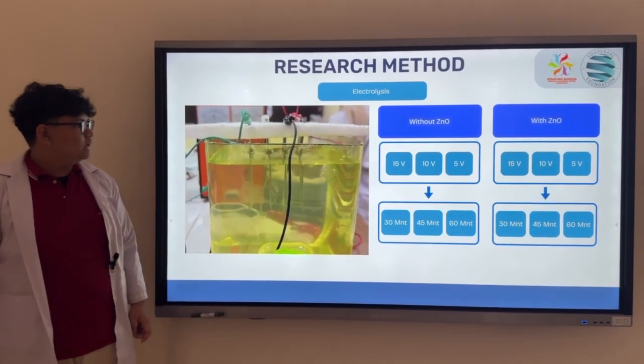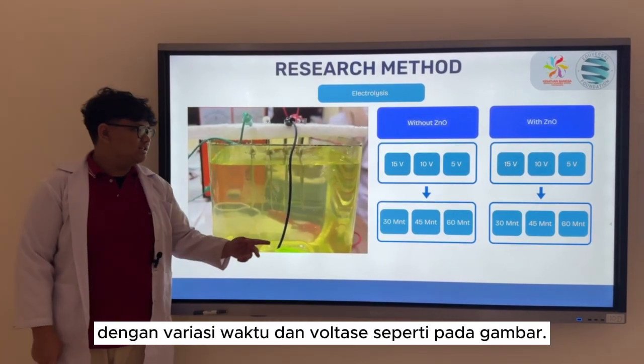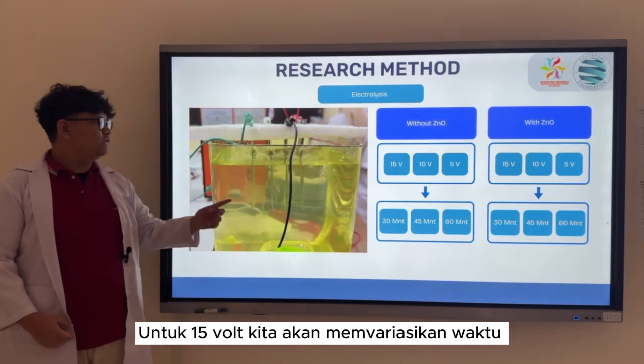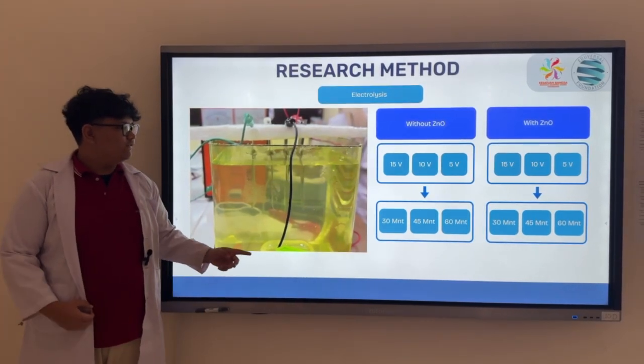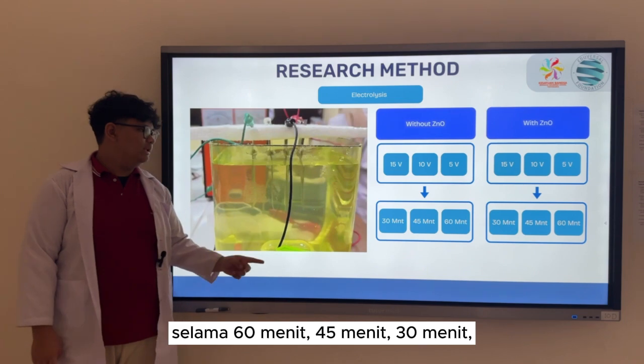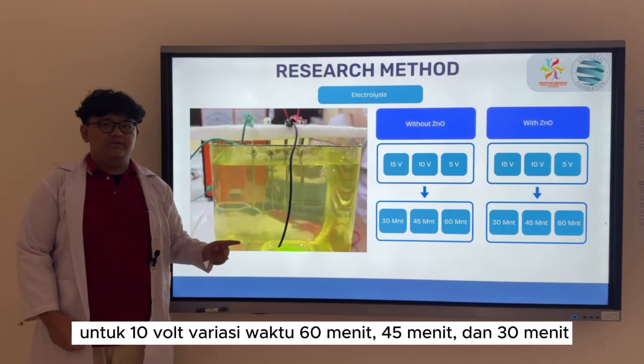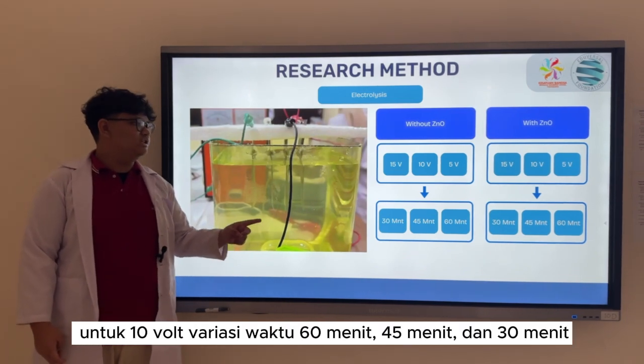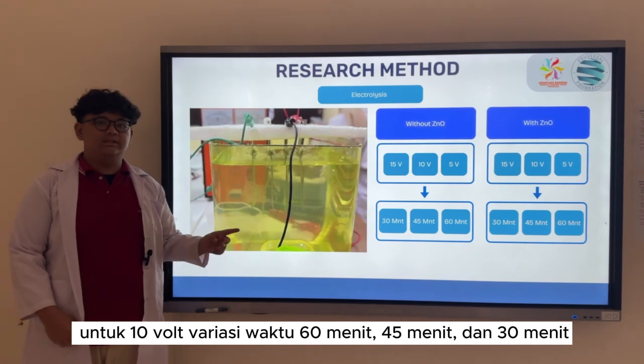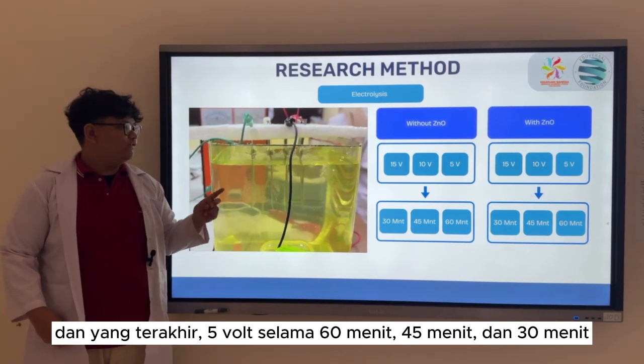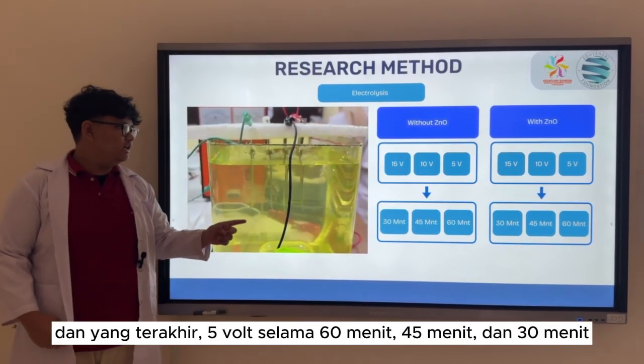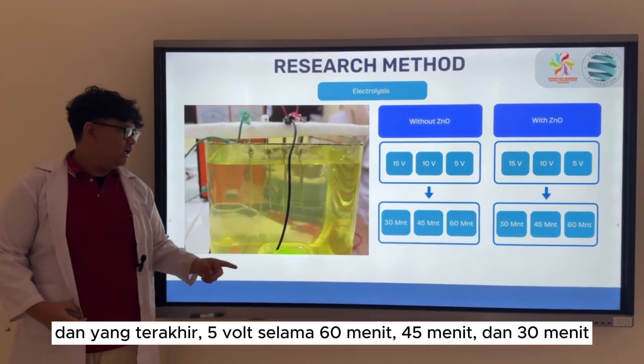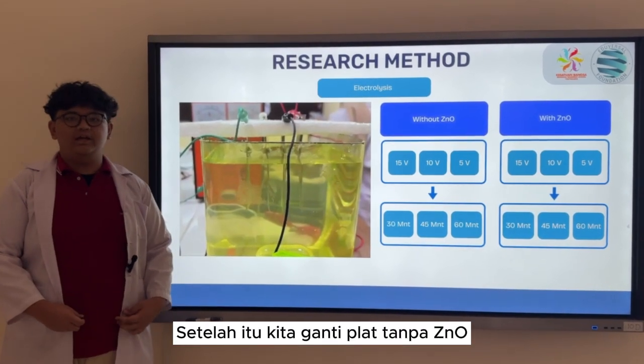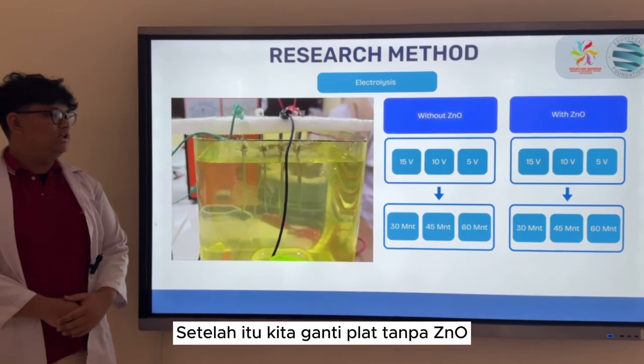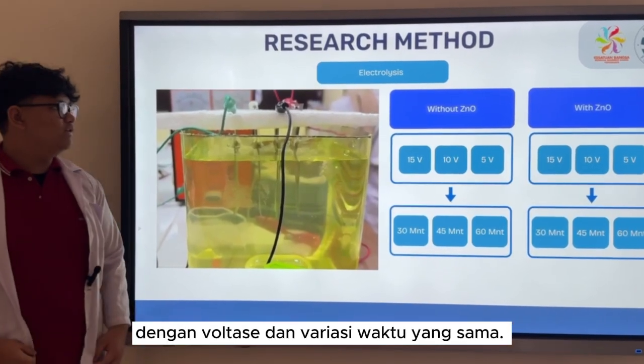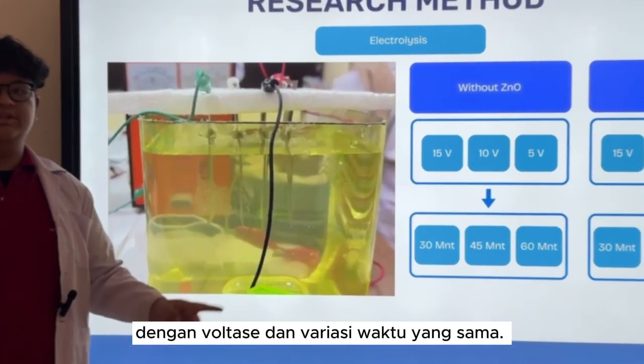For the third step, after the plate has finished heating, we proceed to electrolysis with zinc oxide for its state, with the time variation and voltage as shown. For the 15 volt, the time will vary from 60 minutes, 45 minutes, and 30 minutes. For 10 volt, the time will vary from 60 minutes, 45 minutes, and 30 minutes. And lastly, for the 5 volt, the time variation is 60 minutes, 45 minutes, and 30 minutes. After that, we switch to the plate without the zinc oxide with similar volt and time variation.